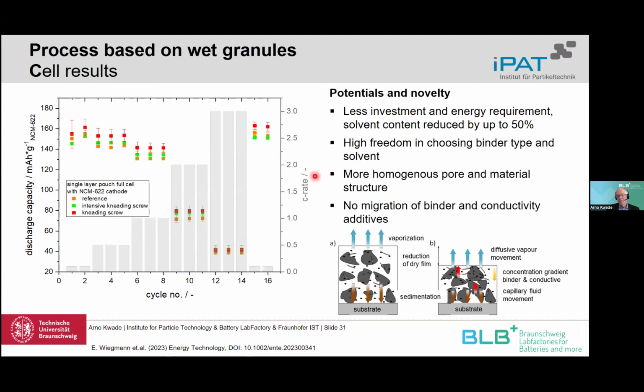And we have a more homogeneous electrode, because that is shown here. This migration is not taking place. Usually during drying, the solvent has to go out of the electrode. By that, it takes carbon black and binder with it to the surface, so that at the end you have a concentrated binder carbon black amount on the surface of the electrode, and less in the bottom where you need it. And this is not the case if we have the semi-dry process.